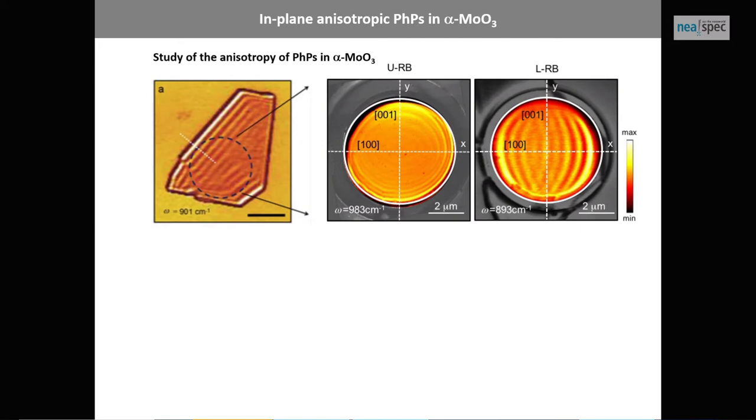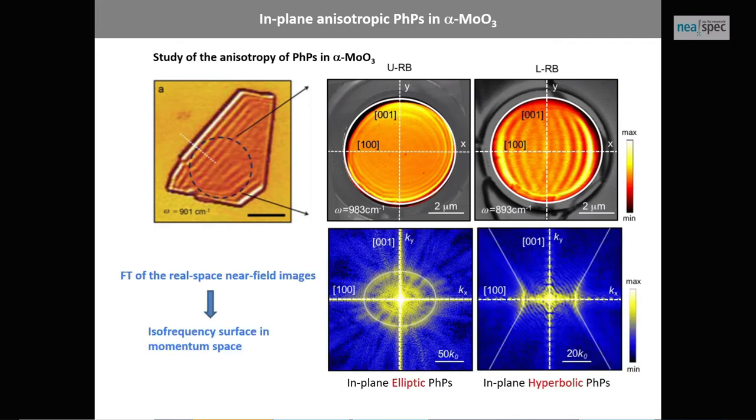OK, how can we see this better? Well, we made a disk, and then we probe, you know that with SNOM and polariton imaging, we do echo detection. So we launch the polaritons, and then we measure what is reflected back to the tip. So the best way to understand how polaritons propagate along different directions for us was to make a disk and probe all directions.